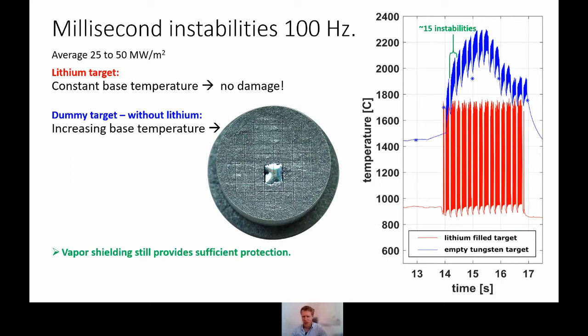So what can we conclude from this? Well, I would say first, vapor shielding still provides sufficient protection in this case. And keep in mind, the loading here is really quite severe. If you would calculate this as an average heat flux, this is with a wide margin of error, I should say, but it should be somewhere between 25 and 50 megawatt per square meter. It is in this ballpark. And keep in mind, in a fusion reactor, the steady state heat load that we aim for is about 10 megawatt per square meter. So this is well above that.